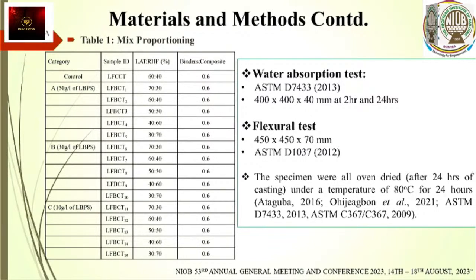Then we vary laterite at the same proportion. Then 10 gram per liter, and we vary laterite and RHF at the same proportion. The binder composite remains 0.6 all through. For the water absorption test, we use the ASTM D7433 2013 edition as our standard for check, and the sample